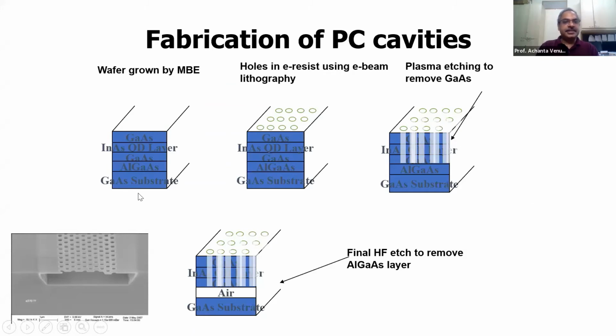For example, you can start with an MBE-grown Stranski-Krastanov quantum dot sample. These are indium arsenide quantum dots, which are capped with gallium arsenide. You spin coat your resist, do standard electron beam lithography to pattern holes in the resist, then etch these holes up to the aluminum gallium arsenide layer, which is called a sacrificial layer, because of the higher aluminum content. You have etch selectivity between the gallium arsenide and AlGaAs just by HF etching, so you can remove this aluminum gallium arsenide and get a suspended structure.